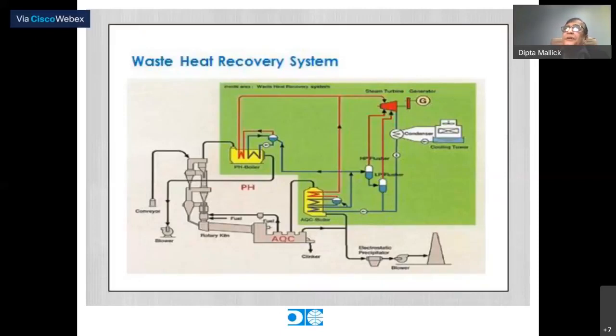You have some heat at some temperature, you have another heat at some temperature. So what can be the optimum temperature of the steam so that you get the maximum electrical energy out of the heat energy that is available? That technology is mature and available. And one of the other very special features of this turbine is that it's not the traditional turbine where steam enters and then exhaust gets out. This is an injection turbine where steam at various pressures, at 2 or sometimes 3 pressures, are injected into the turbine so as to get the best efficiency from the turbine.